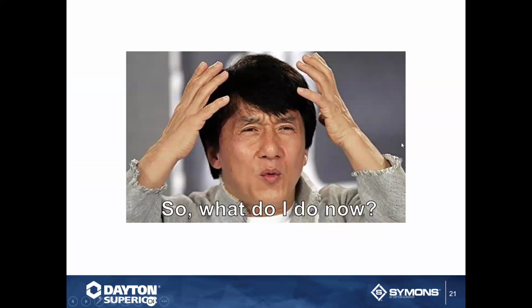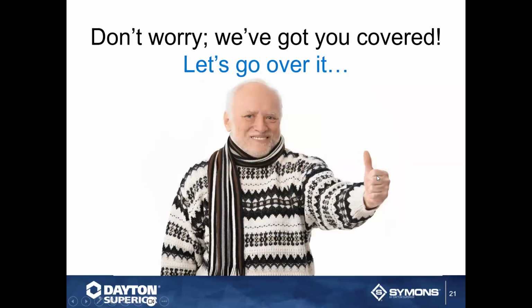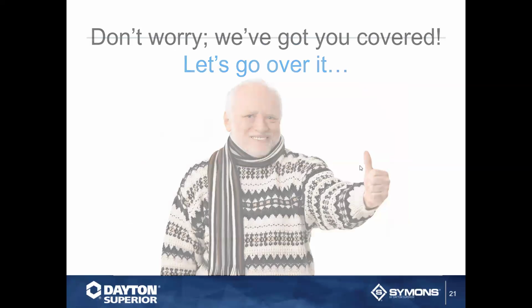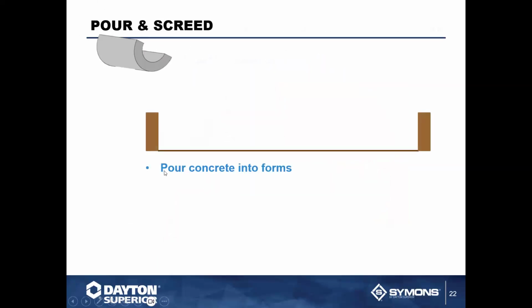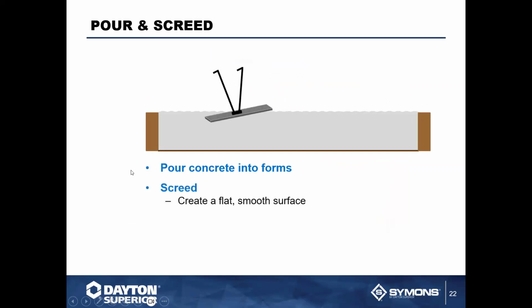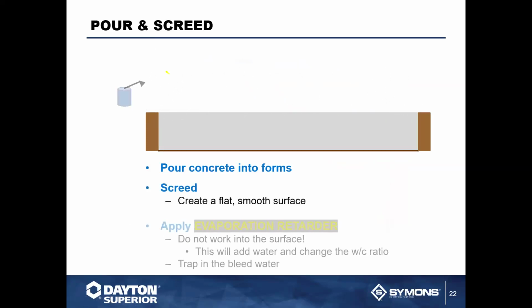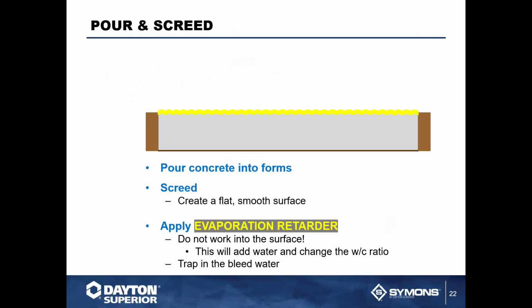So what do you do now with all this information? Well, we've got you covered. Let's go over it real quick. You come in, you pour and screed. You're going to pour your concrete and strike it off. You're then going to apply your evaporation retarder on top of it. Do not work it into the surface. Let the material work. It's going to mix with any of the bleed water that comes in and help trap that water on the surface of the concrete. This will change a little bit of the water cement ratio, but it will trap the bleed water within the slab.